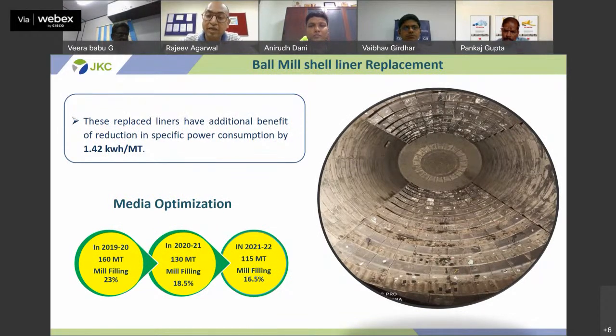Sir, previously we had conventional liners, and these were replaced by specific thin liners, T-shaped thin liners, and through this we got a benefit of 1.42 kWh per metric ton specific power. This also helps us optimize our media pattern. In 2019-20 we were at 23% media loading, and as of now we are at only 16.5% media loading, and this gives us the benefit in specific power.